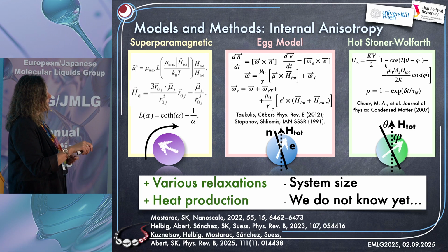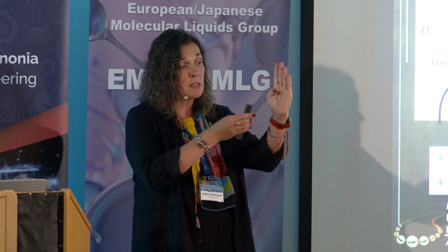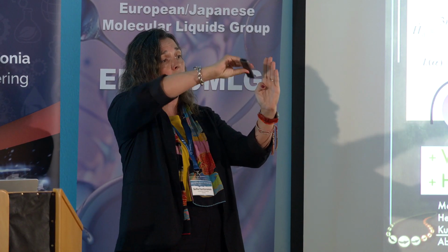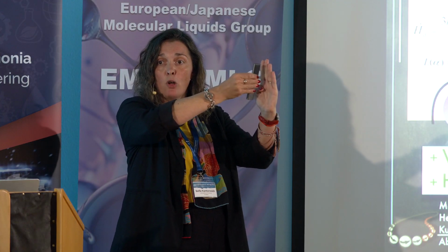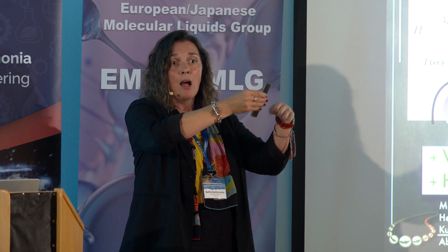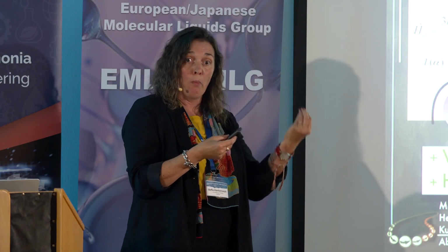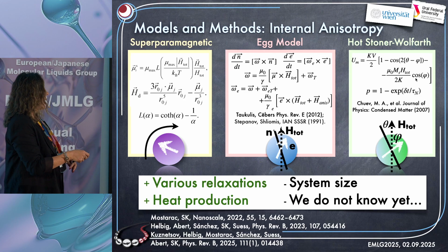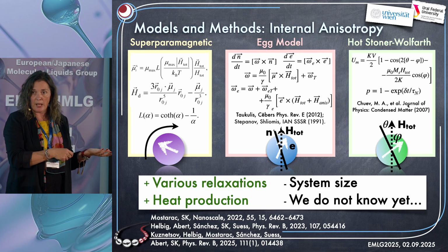And this relies on two minima states. So you have an easy axis of magnetization. There is a crystalline-lattice favorable orientation of the magnetization, and it can only switch within this orientation, depending on the energy barrier. However, for nanoparticles, you need to add thermal perturbations, so you add on top of it a probability of a switch that is not related to an applied magnetic field.